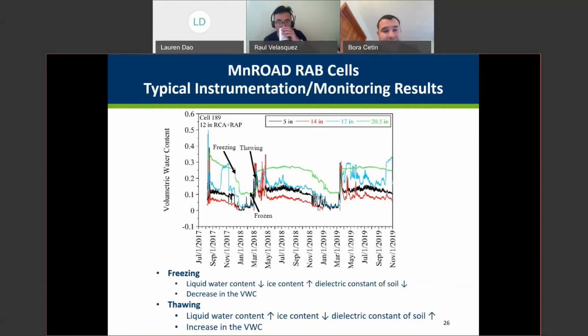And here we labeled it as freezing, where you see a steep decline on the curve. That shows that something is happening to the water content in the soil. If you look at the time interval there, it started in January, actually even before, in December. That means the weather is getting colder, the soil starts getting below freezing temperature, and of course the volumetric water content measurements decrease significantly, which means ice starts forming. And then it stays stable, frozen for a while during that period, which gives us the frozen time of that particular depth in that particular test section.